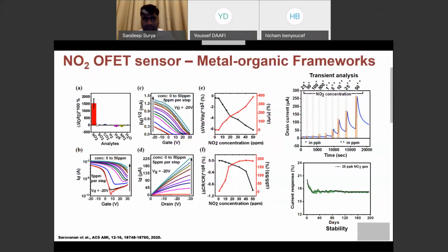These are the complete parameter extractions that we have done using the OFETs in this case. So like I have explained before, the addition of MOF onto the structure of OFET with PDBT10 not only increased the selectivity with respect to other interferents like H2S and ammonia, but it also increased the sensitivity more or less like 6 orders more than the PDBT10 device alone. The corresponding graphs that we show here are for different concentrations of the NO2 exposed. Here what you see is the drain saturation current, and in this case it's the on current change along with the shift in the threshold voltage in the transfer characteristics.